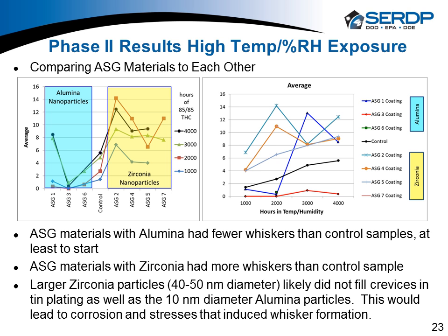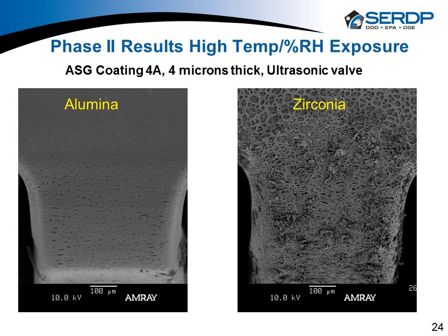So we kind of had to take a step back. We kind of reinvented the wheel. We should have learned, if we could have gotten a zirconia nanoparticle that was 10 nanometers, this might have been different. But, of course, we didn't. Our nanoparticle was in the 40 to 50 nanometer range. It just didn't perform very well. If I go forward again here to slide 24, you can see a clear difference. The alumina with its smaller nanoparticle and coming out of our spray equipment, much better than this kind of webbing, just not the same surface, not the same deposition of coating.